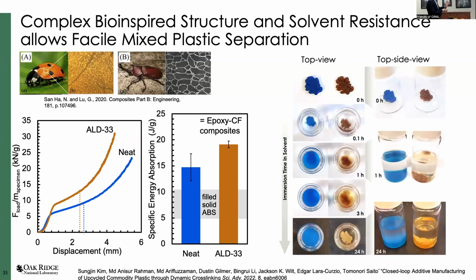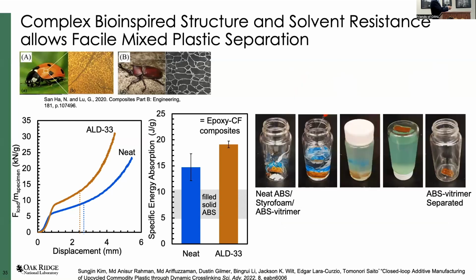Also, this is not soluble. So again, it's cross-linked. The original material is nicely soluble in solvent. It can dissolve. This is not. So we had an idea, what if we have a mixture of plastics? Styrofoam, neat ABS, ABS vitrimer, and this is our product. You mix it, we can separate it out. Everything else is gone, but this stays. So we can recover. That's the pathway, we can recycle this kind of material too.